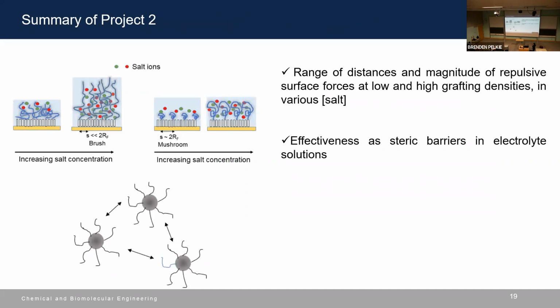So with that, we looked at the different ranges of distances as well as the magnitude of the repulsive barrier generated by both high and low grafting density of polysulfobetaine chains. And we showed that even at low grafting density, or mushroom-like chains, the repulsive force can be substantial. So they can also have potential application for stabilizing nanoparticles. And also, understanding that the effectiveness of a steric barrier in electrolyte solution can be affected by the ionic strength dependent swelling behavior of the zwitterionic polymers.